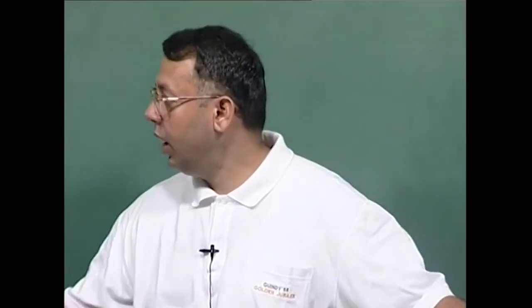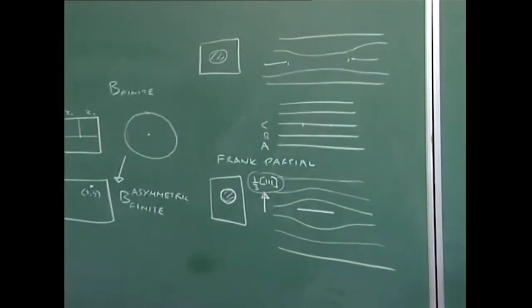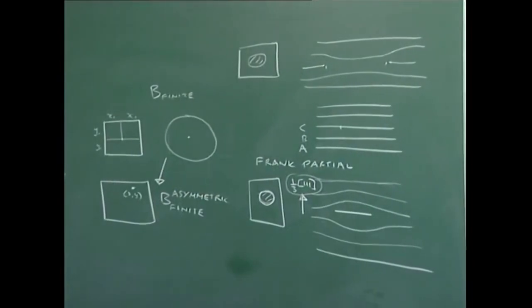But those kinds of dislocations are different from these, because now this is a pure edge dislocation which is curved. Therefore, it is possible to have curved dislocations that are of pure edge character, while it is not possible to have a pure screw dislocation which is curved. In that case the dislocation lies on the slip plane, in this case it does not lie on the slip plane and it is not glissile.